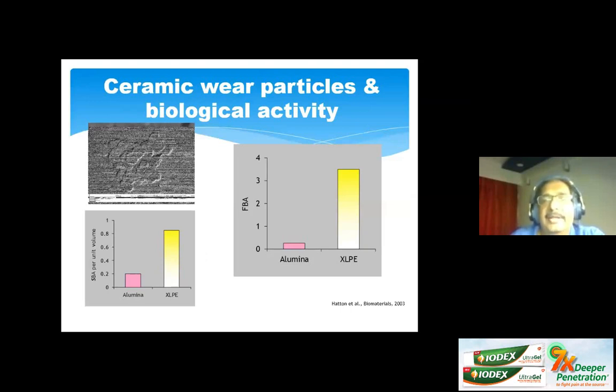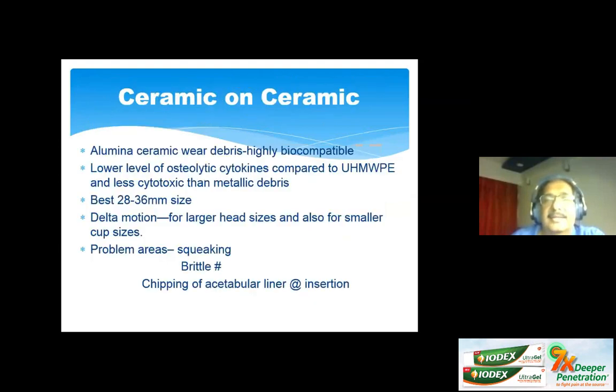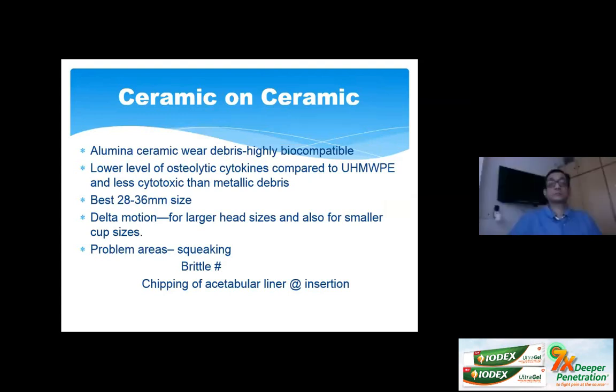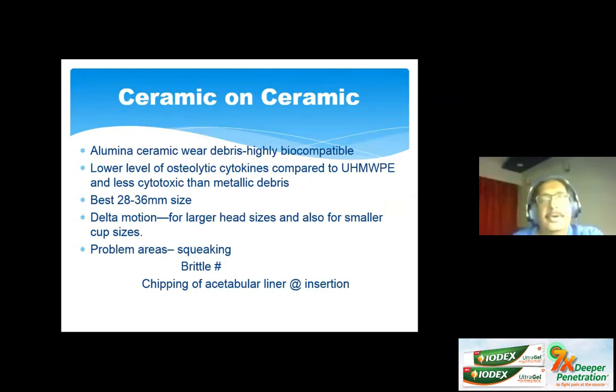And the biological activity, again, is much less of these ceramic alumina particles. The biocompatibility is much higher. There's a much lower level of osteolytic cytokines compared to even ultra-high molecular weight polyethylene. And the best option is a 28 to 36 millimeter head size. There is a situation where a larger ceramic head has been used in what is called the delta motion type of hip, which we will discuss when we discuss the uncemented hip systems.